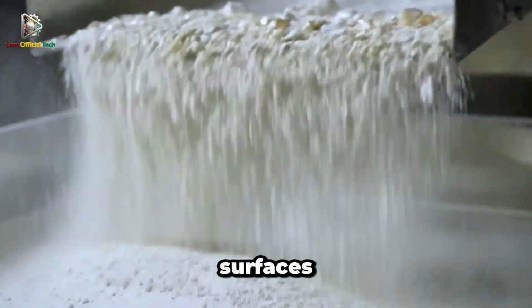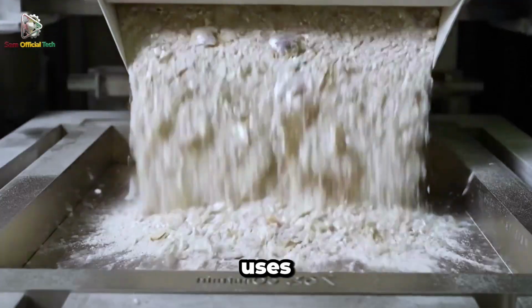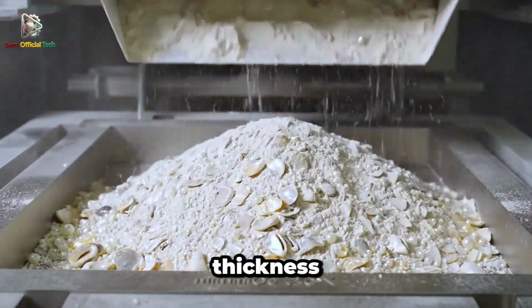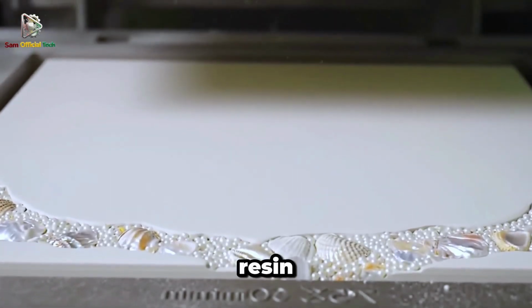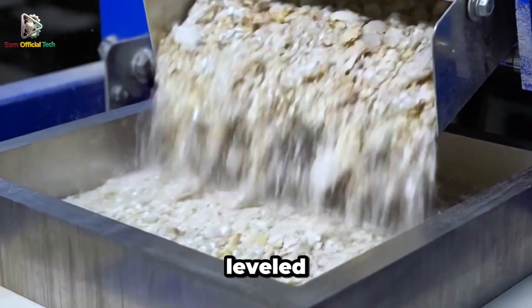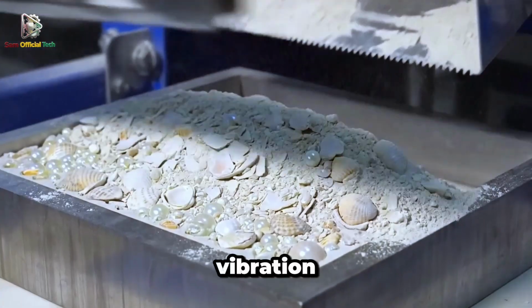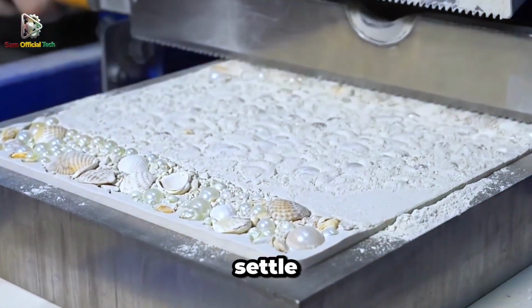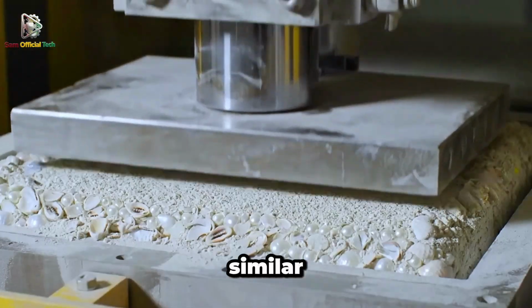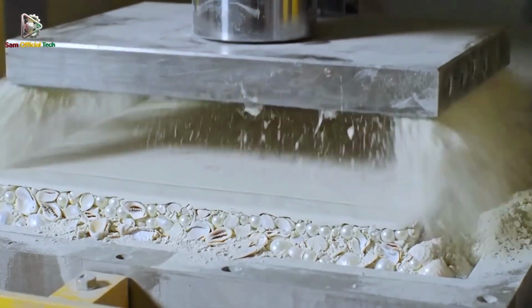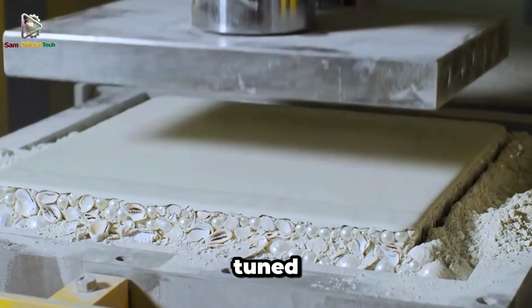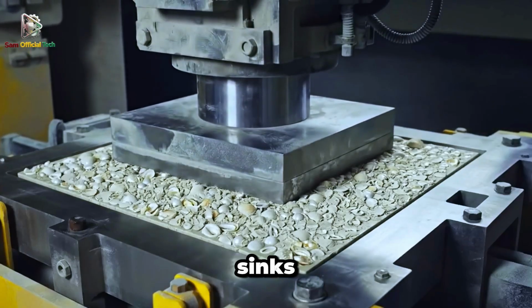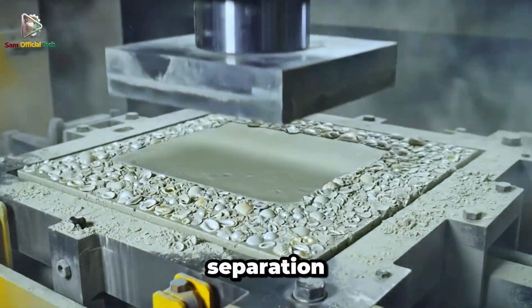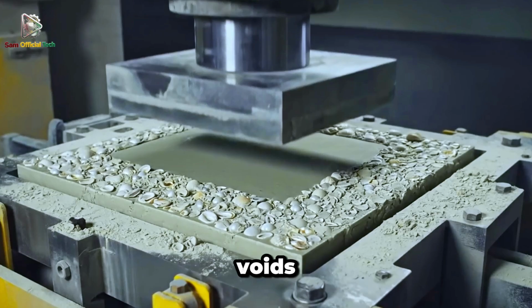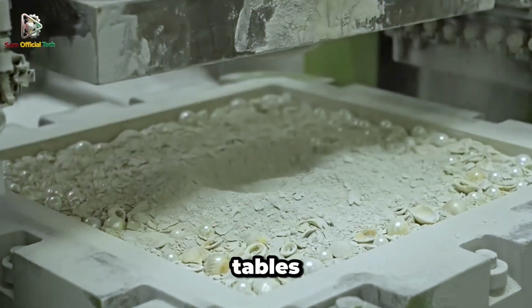For cast surfaces, the factory uses molds or perimeter frames to define thickness. The shell resin mix is poured onto the substrate, then leveled with screed bars. Vibration tables shake the assembly to settle chips and release trapped air, similar to concrete consolidation. The vibration frequency is tuned. Too much vibration sinks chips and causes separation. Too little leaves voids and weak bonding for inlay tables.